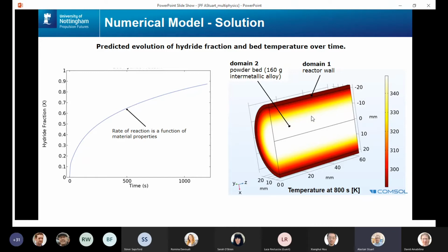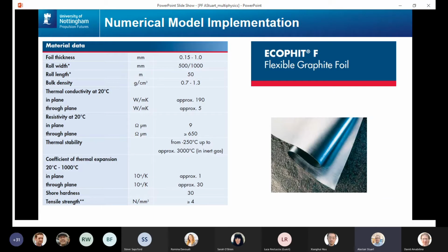And I can see here that there's an issue of heat transfer. This reaction is very slow, and I might be trying to meet a certain rate of hydrogenation, because I'm coupling this container, perhaps, to an electrolyzer. So I can then think about how to improve this. For this example, I'm going to use some fins. I'm going to make them out of Ecophit F, which is an expanded natural graphite. Fortunately for us, the manufacturer has done the characterization of the material already, so I'm showing some properties of it here.